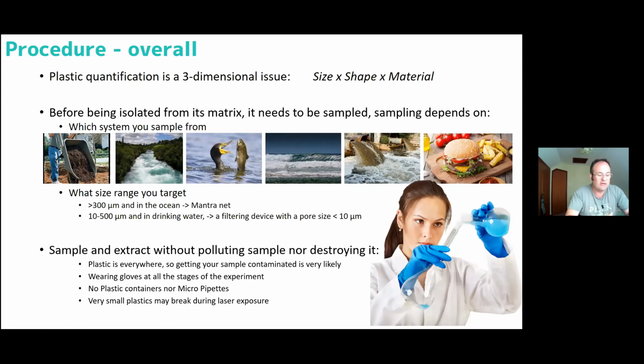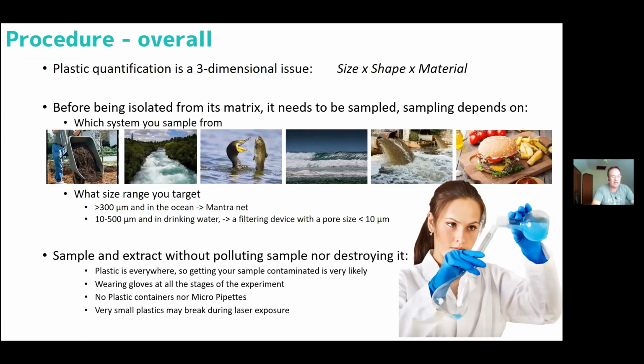So you've got to take some very controlled steps to do so. You need to wear gloves all the time. You can't use any plastic containers with your samples or micro pipettes. And also, when you're measuring, if you're using a high-powered laser, for example, that actually might destroy or break down your small particles.